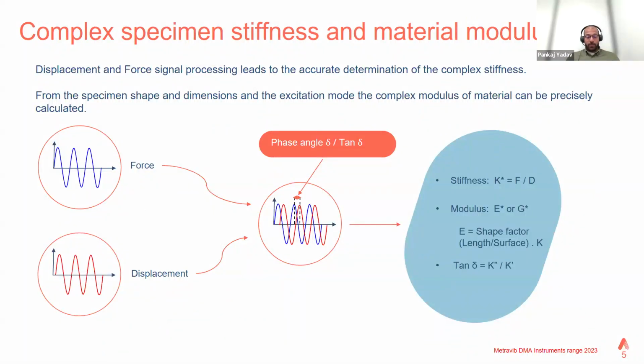That means when we apply a small load or displacement and the response of the material is measured, there is a delay in getting that response, which is denoted by an angle called delta, or the tangent delta, which is also known as the phase angle. What happens later on is that these displacement and force signals are processed, integrated in the software itself, and it provides us the stiffness of the specimen, and hence the complex modulus and the tangent delta of the viscoelastic materials.